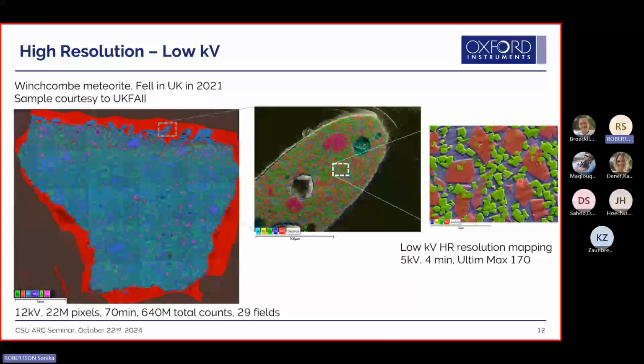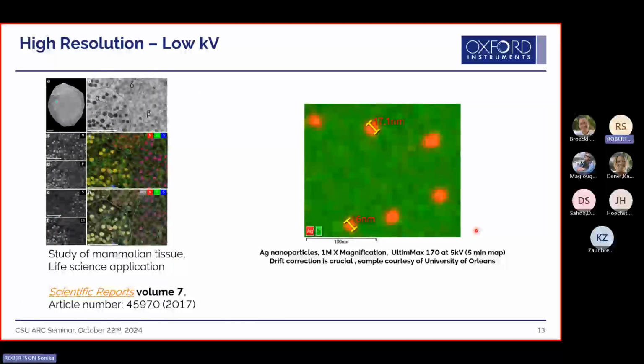And you could further do high resolution at 5 kV just in 4 minutes with that detector. So you're able to characterize, again, scale bar here is not that crazy. It's only 10 microns. So let's go to crazy. This is sub 20 nanometer features, again, characterized with the same detector. You're starting to see the pixelation show up.